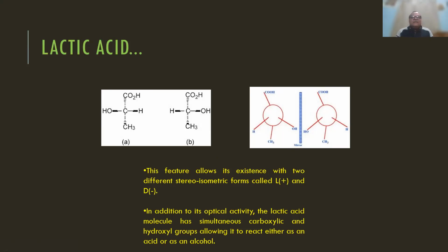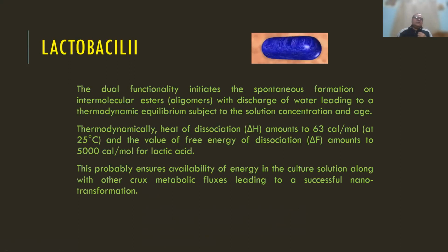So what is the advantage? The advantage is that this dual functionality initiates the spontaneous formation of intermolecular esters, oligomers, with discharge of water, leading to a thermodynamic equilibrium subject to the solution concentration and age. We took advantage of this very statement. We incubated bacteria for 72 hours in the presence of different concentrations of a carbohydrate, that is glucose, and we got different results. So why did it happen?